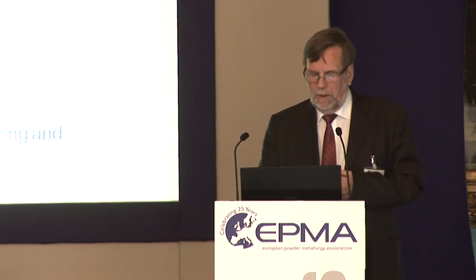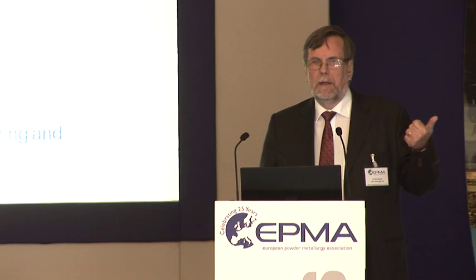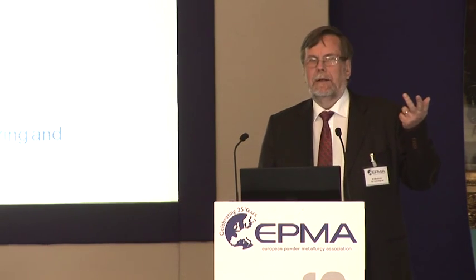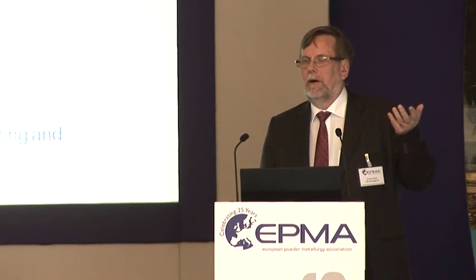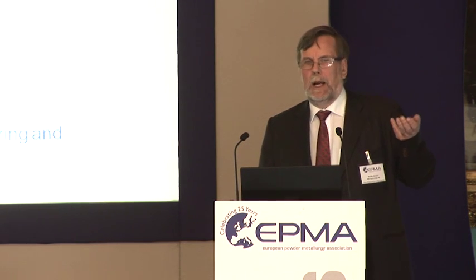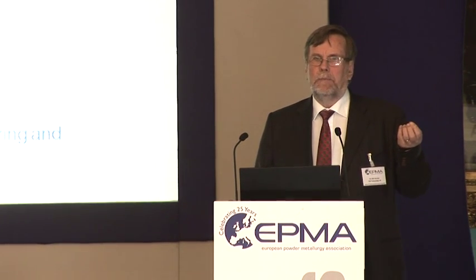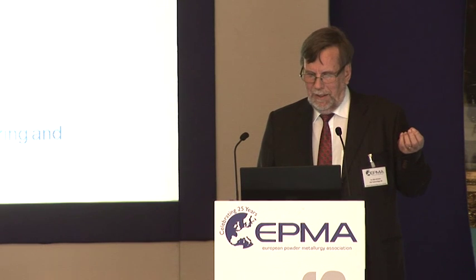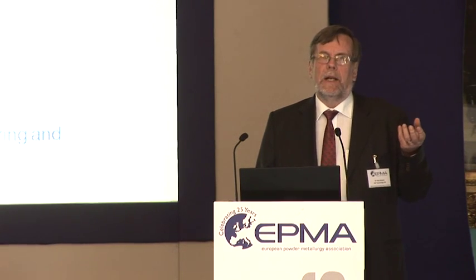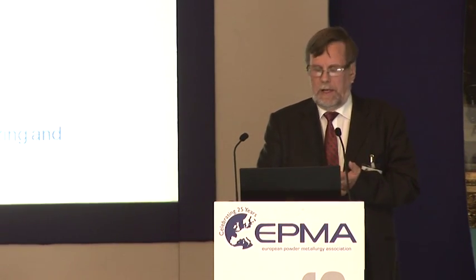This is a material from Sandvik Heating Technology, Kanthal, called APMT. It's a powder metallurgy product. It's dispersion strengthened, probably with something like yttria. And it's designed in such a way that when oxidized, it's not forming a chromia oxide film, but an alumina oxide film. This means that the strength is improved by the dispersion hardening of this FeCrAl alloy, with high creep strength and form stability, and the alumina surface layer gives protection in oxidizing, sulfidizing, carburizing, and reducing atmosphere.